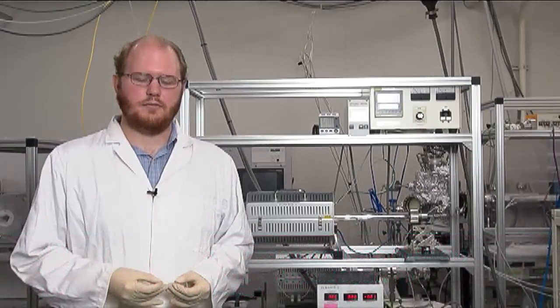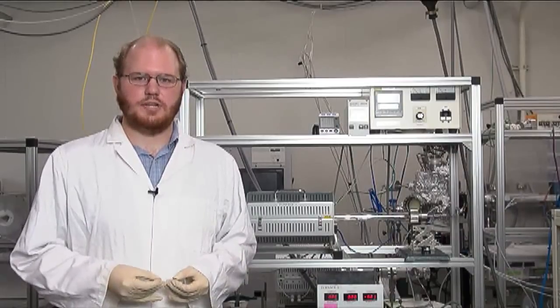Large area single crystal graphene avoids many of the problems of domain boundaries, such as reduced charge carrier mobility and mechanical strength. It may be also possible to alter the electronic conditions of graphene by applying mechanical strain, and this has particular applications where a band gap is required, such as photovoltaics or transistors.